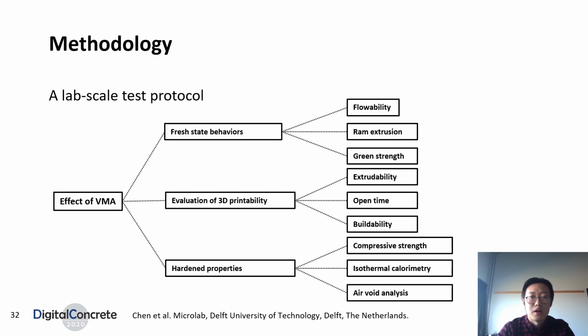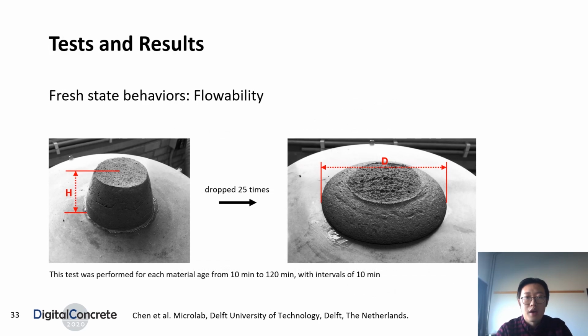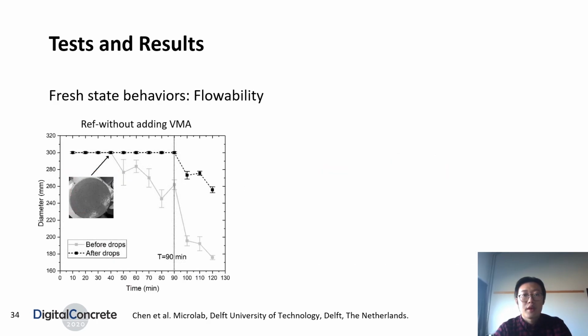We proposed a lab-scale protocol to investigate the effect of VMA on 3 specific aspects: fresh state behavior, 3D printability, and hardened property. For fresh state behaviors, how the flowability changes with time is studied. We measure the height of the molded sample for the mixtures containing VMA. After 25 table drops, the diameter of the sample is measured. But for the REF mixture, only the diameter of the sample was measured before and after table drops. The flowability change can be clearly observed, especially after 90 minutes of water addition.